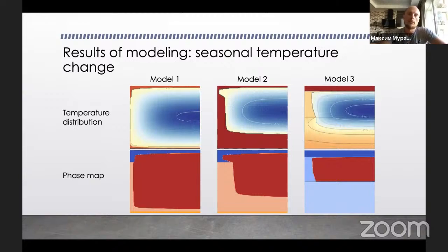On this slide, the results of modeling for seasonal temperature change for 3 models. We placed the ice island into a medium with air temperature 10 degrees Celsius for 150 days, and observe the temperature distribution and phase map after this time period. The results are represented on this slide.